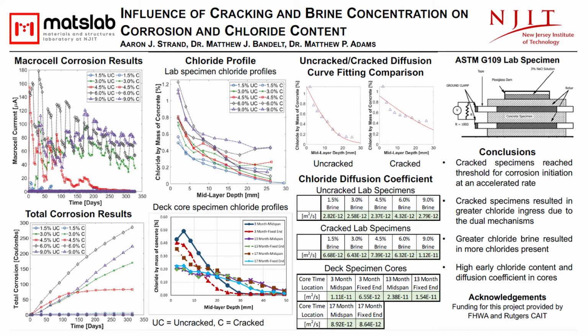The total integrated current, or total corrosion, was also calculated. The specified corrosion threshold in ASTM G109 of 150 coulombs was only reached for the specimens that were cracked and ponded with a brine concentration of 3, 6, or 9%. For the uncracked specimens during the testing period, the total corrosion did not exceed the value of 1 coulomb for any of the tested specimens. This shows a major difference between the rate of corrosion in cracked and uncracked systems.